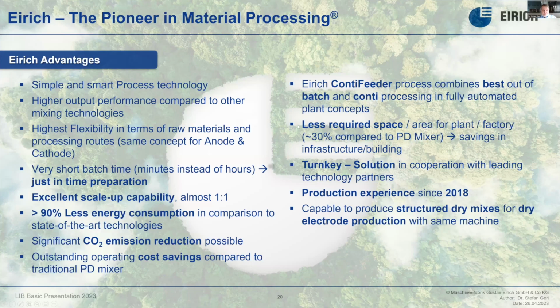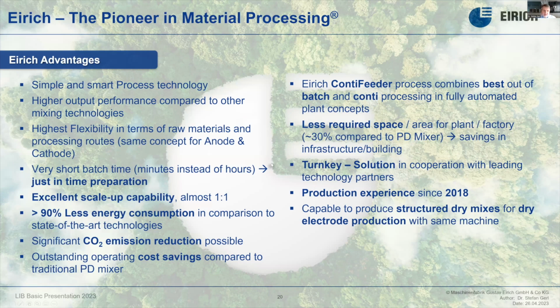To summarize my presentation, you have seen that we have a simple and a smart process technology. We have significantly higher output performance compared to other mixing technology, especially like the PD mixer. We have highest flexibility in terms of raw materials and processing routes. This means, as you have seen, you can make wet, you can make semi-wet, you can make dry, you can make different dry routes. We have typically a very short batch time, just minutes instead of hours. We have an excellent scale-up capability, 90% less energy consumption in comparison to state-of-the-art technologies. This means also a significant CO2 emission reduction and higher sustainability.